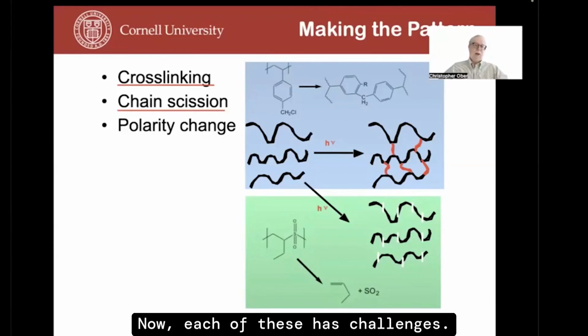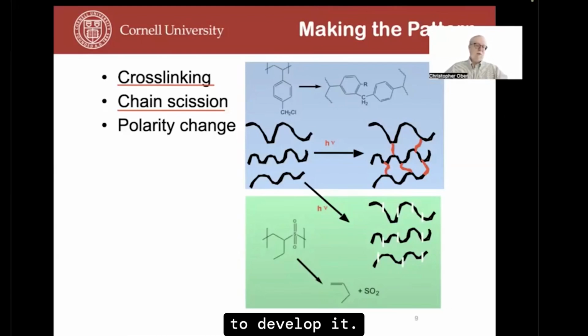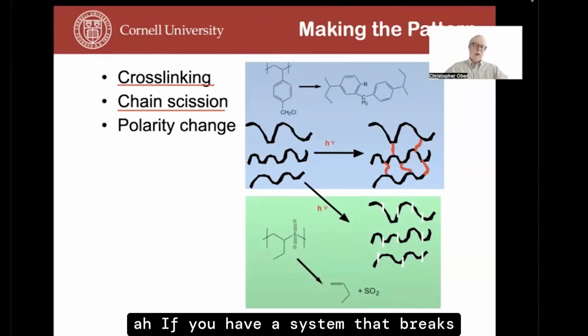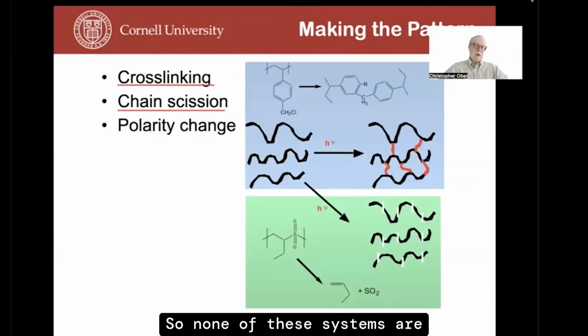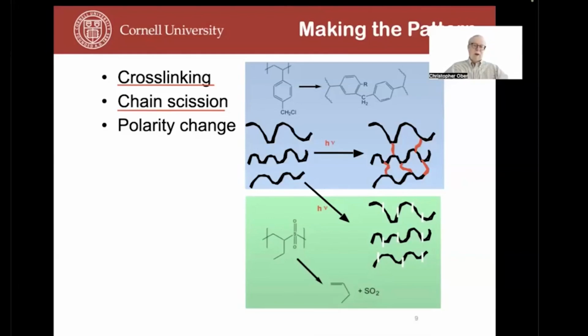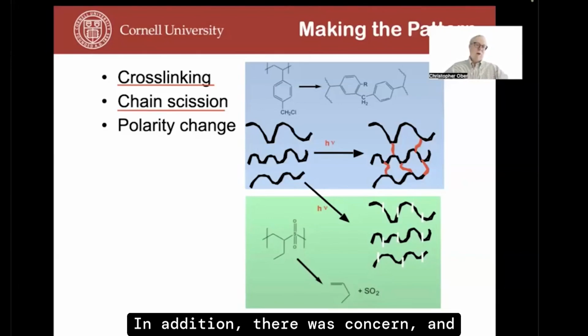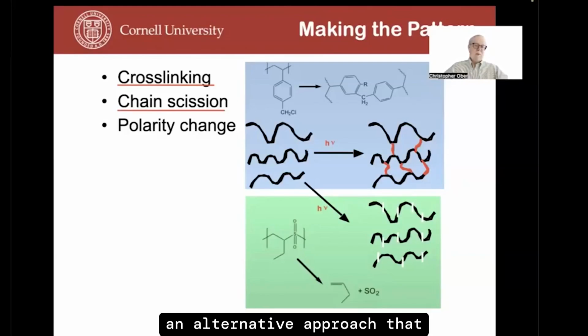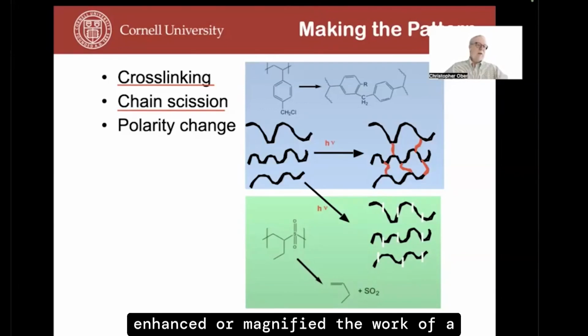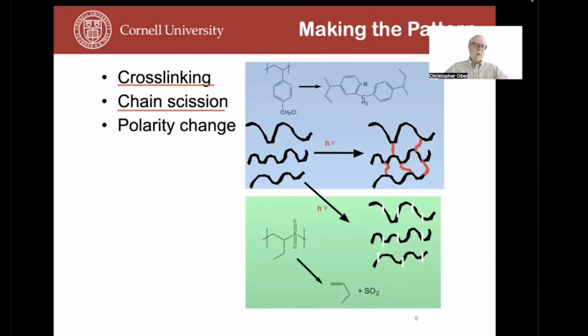Now, each of these has challenges. If you take a negative tone system, it may still swell from a particular solvent if you're trying to develop it, and that can lead to imperfections. If you have a system that breaks into small pieces and it's volatile, in some of the vacuum systems and high energy radiation that's used, it could lead to deposition. So none of these systems are perfect. In addition, there was concern, and I'll say more about this shortly, the concern in the 80s that there wasn't going to be enough radiation from a particular light source. And so there was a need to develop an alternative approach that enhanced or magnified the work of a single photon.